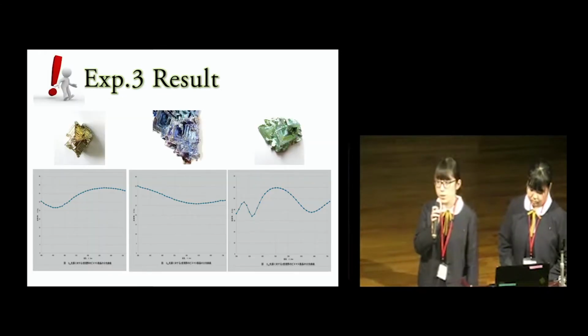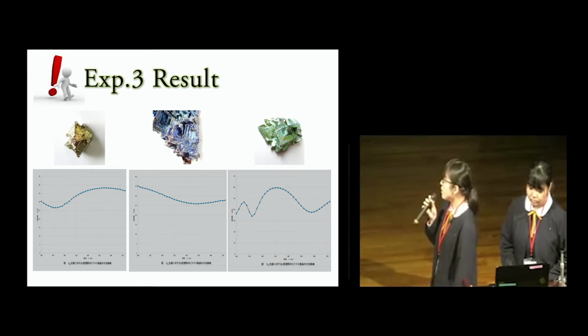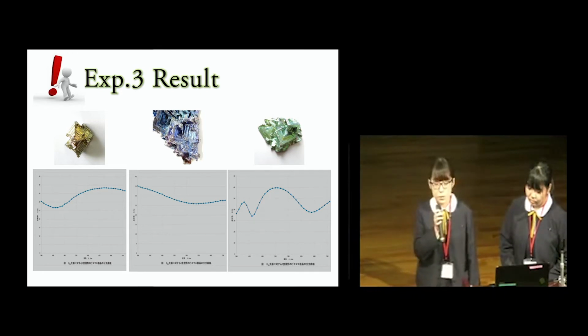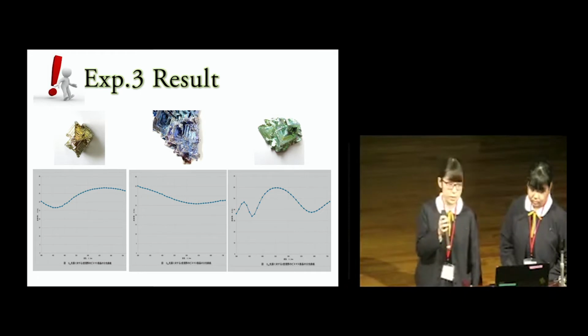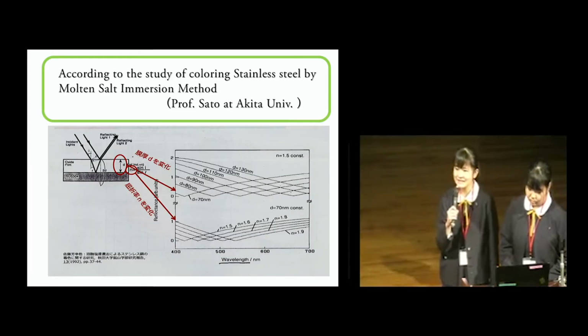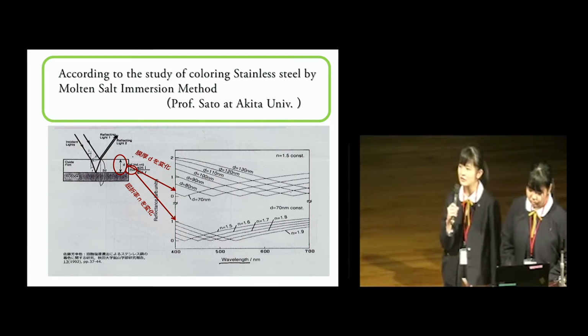The relationship between the color of the crystal and the absorption spectrum is shown on the slide. From the left, the results are for gold, blue, and green crystals. The absorption spectrum graphs are different and very interesting because of the different crystal colors. According to Professor Sato's research, there are only 3 types of absorption spectrum graphs in the simulation, considering the thickness of the oxide film on the metal surface and the refractive index of the oxide film. We know that the 3 types of spectrum graphs are a downward type, a rightward type, and a type with a mountain.